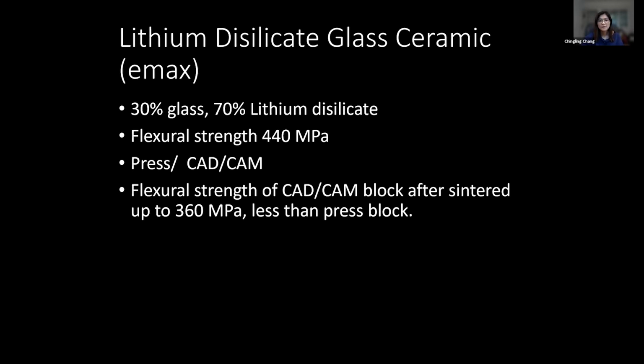And now they have come up with the lithium disilicate glass ceramic. That's getting very popular now. They are basically being used for most of the cases now. They have only 30% glass and 70% lithium disilicate, so they greatly increase the flexural strength up to 440 megapascal. And the way to fabricate it is also pressed ceramic, or also using a CAD/CAM system. But comparing these two fabrication techniques, the press technique still has a higher compressive strength and flexural strength.